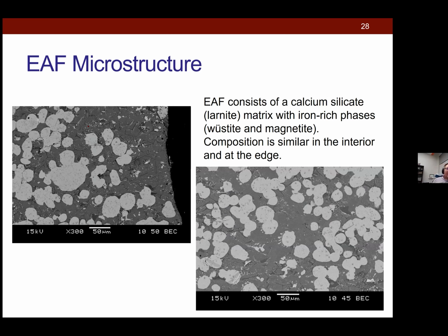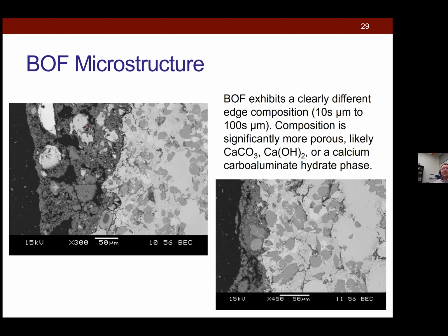When we looked at the microstructure, we did the strength study again and asked, why are we seeing these differences? We found that the source that gave us the highest strength, this specific source of electric arc slag, has a fairly uniform microstructure, without a lot of variability. Compare that now to this slag that gave us the lowest strength. We found there was an outer layer of high porosity and different composition. In the literature, people have found that composition to be calcite, sometimes calcium hydroxide. One study claimed it was a type of CSH. Other people say it's a calcium carboaluminate phase.